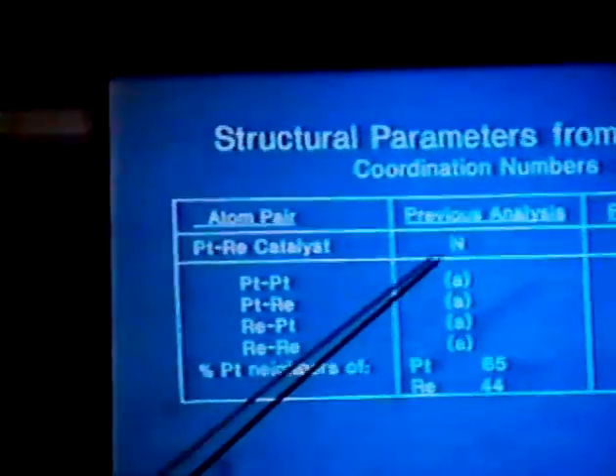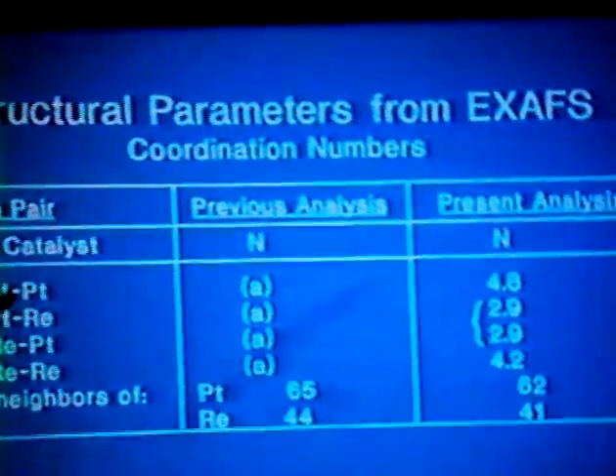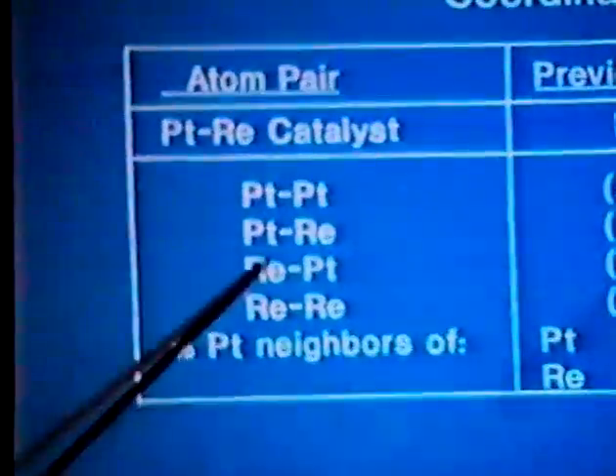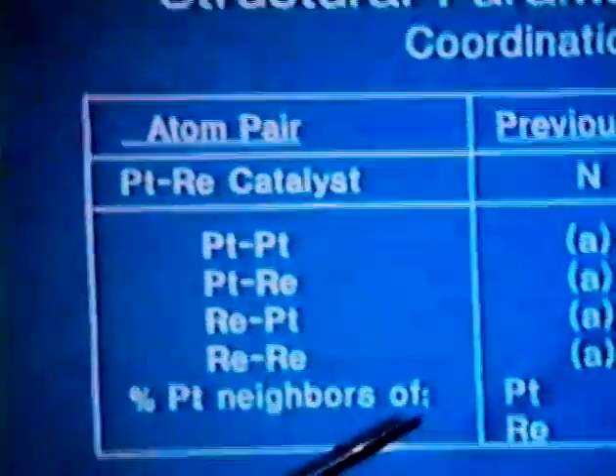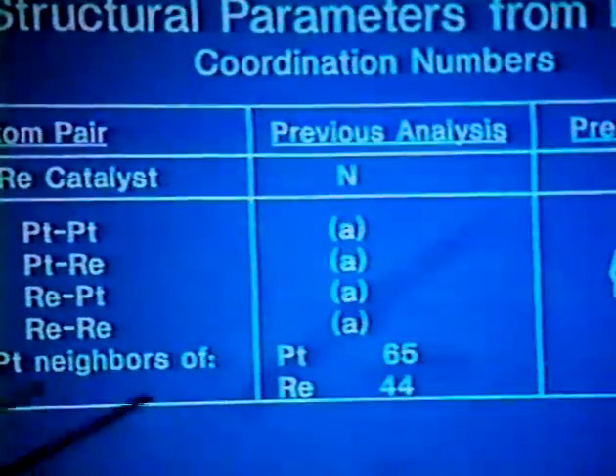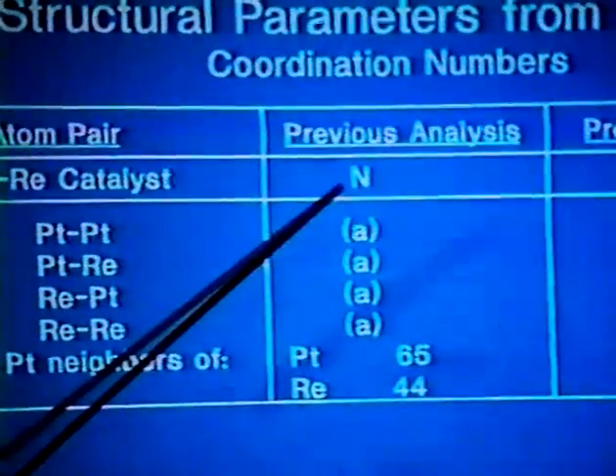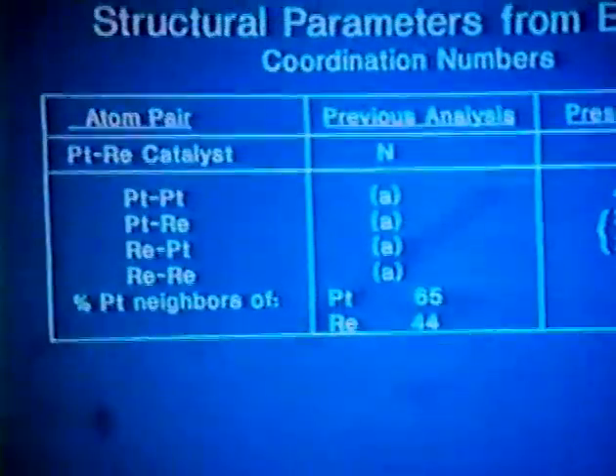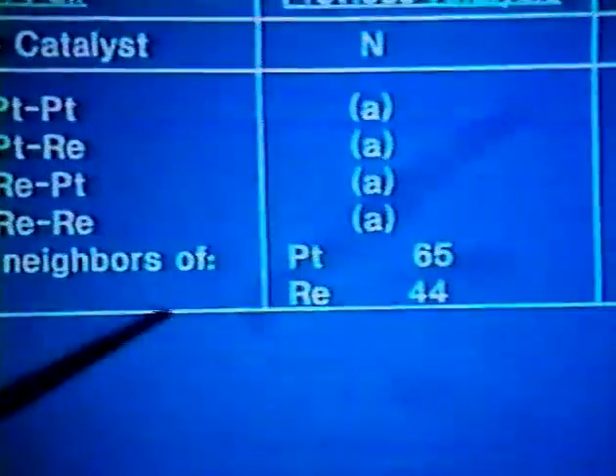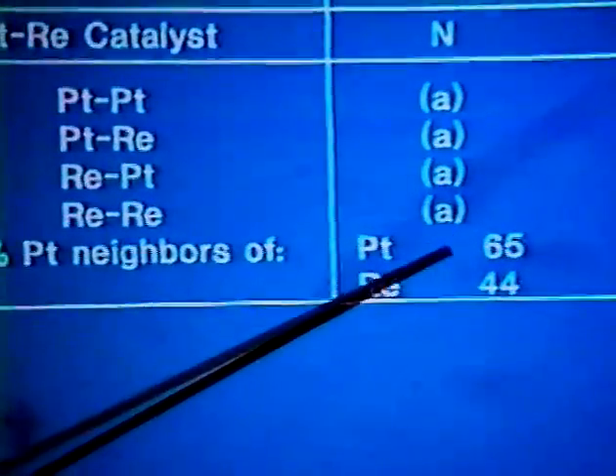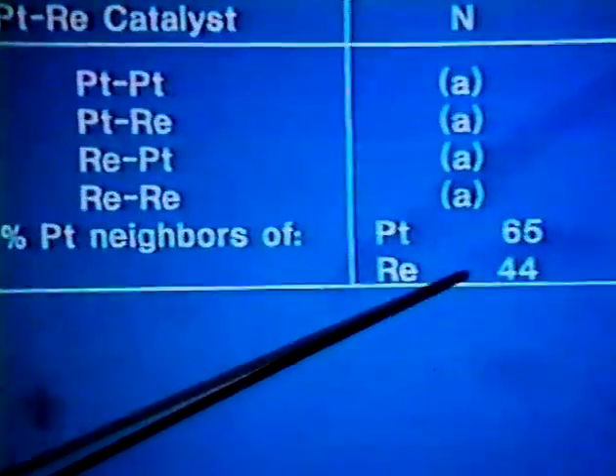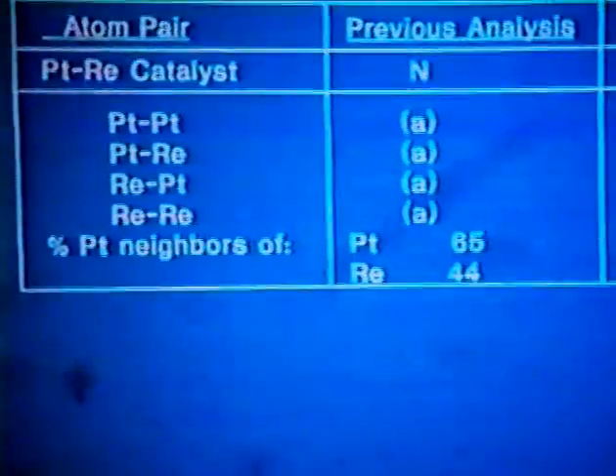Now, these are structural parameters from analysis of EXAFS. They happen to be coordination numbers. Atom pairs over here in a platinum-rhenium catalyst: the atom pairs are Pt-Pt, Pt-Re, Re-Pt, and Re-Re. In a previous analysis where the interatomic distance was fixed as I've described, determining these various coordination numbers, I say couldn't determine them because the coordination numbers were correlated with another adjustable parameter, and the correlation was so strong that it was just indeterminate. We artificially reduced the number of variables by determining composition of the coordination shell, and we found that platinum has 65% platinum neighbors and rhenium has 44% platinum neighbors.